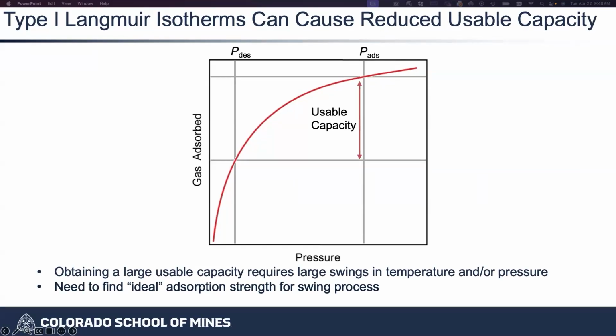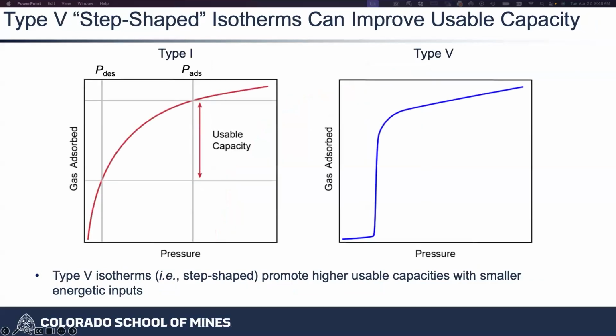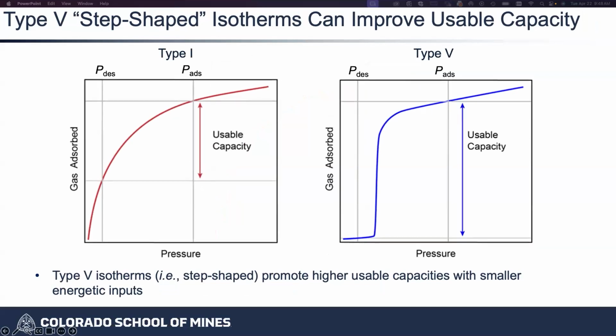And so the actual usable or deliverable capacity in your system is much less than the total capacity. And so what we've been working on is basically trying to find ways that you have a fundamentally different response of adsorption with pressure, where you have basically some minimal amount of adsorption occurring until some threshold, steep adsorption followed by a plateau. And the reason why we'd want that is because when we have our adsorption and then our desorption, all of a sudden the amount of gas that you can actually put into the system is very similar to the amount of gas you can get back out of the system. So you're trying to obviate kind of this core inefficiency in the system.